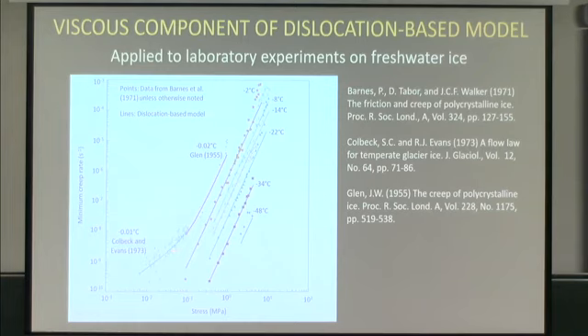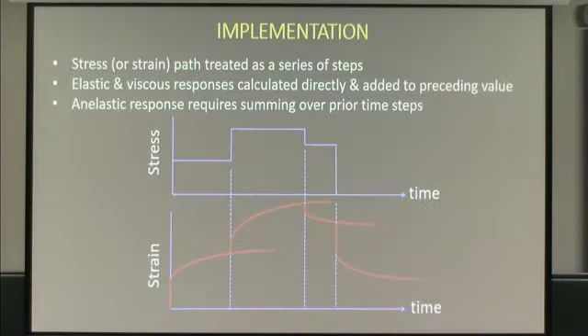This is due to a high initial level of dislocations that causes this deviation from n = 3 behavior. I'm not doing anything with microfracturing, but the deviation at high stresses is power law breakdown due to microcracking. Not addressing that at all. So at any rate, that's pretty cool.